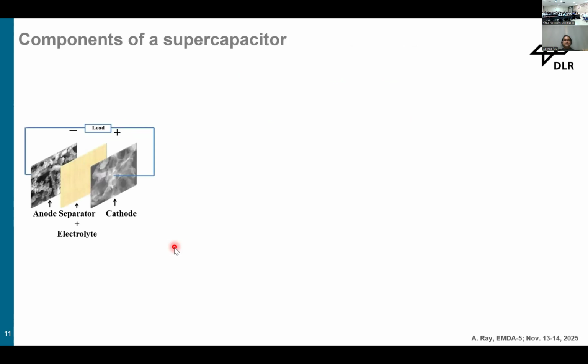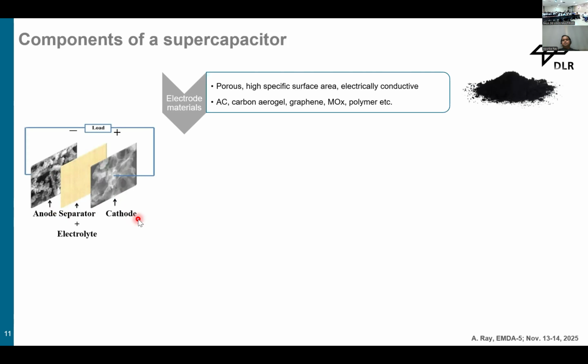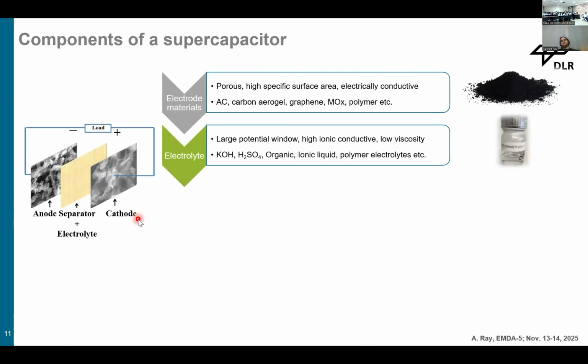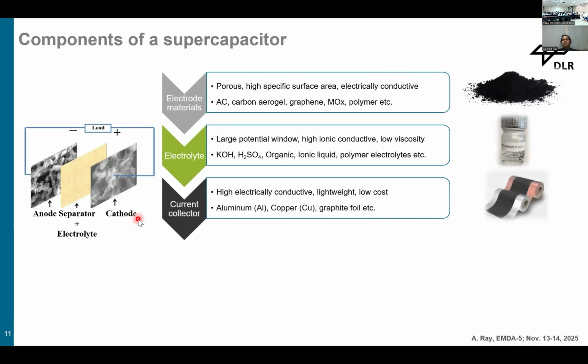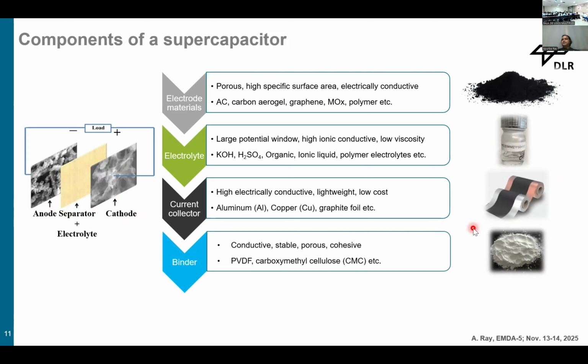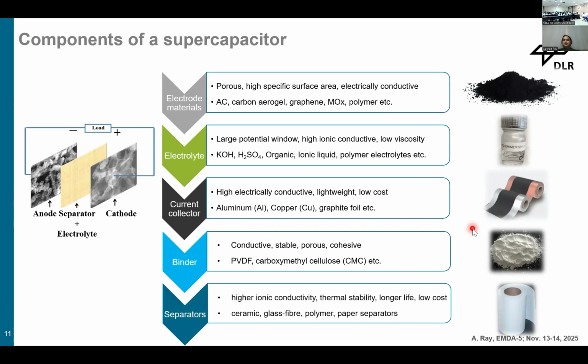The main components of the device are two electrodes, one separator in the middle, and also the electrolyte. So anode, cathode, and separator are the main components. In most cases, different types of carbon based material, activated carbon, carbon aerogel, graphene, are used for electrode material. Different types of electrolyte are used: aqueous electrolyte, ionic liquid, polymer electrolyte. For the current collector for anode and cathode, copper or aluminium is used as the substrate for electrode preparation, and also the binder. The binder also has a very strong influence on the device performance. PVDF is still commonly used, and also the separator. Different types of separator, ceramic separator, glass fiber separator, polymer, paper separator, are used in the device.